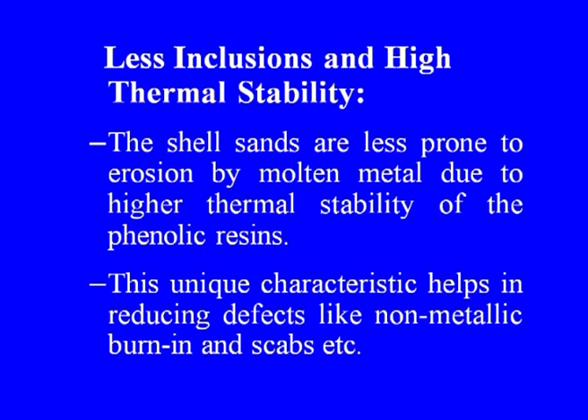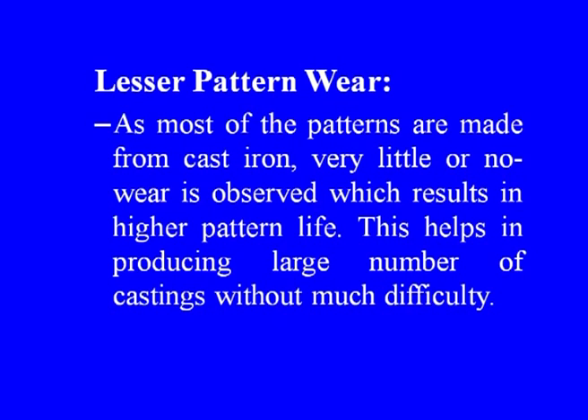Less inclusions and high thermal stability is another advantage. The shell sands are less prone to erosion by molten metal due to the higher thermal stability of the phenolic resins, which helps in reducing defects like non-metallic burn-in and scabs. Another advantage is lesser pattern wear — as most patterns are made from cast iron, very little or no wear is observed, resulting in higher pattern life and allowing large numbers of castings to be produced without difficulty.